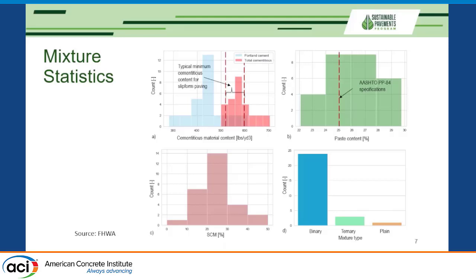Yes, here we go. On the top, I am summarizing the cementitious material content distribution in pounds per cubic yard. Here you can see the red series represents total cementitious content, while this lighter blue, almost invisible, shows just Portland cement. And here we have the recommended typical minimum content of cementitious materials for slip form paving. We can see that we are a little bit higher, on the upper range of this interval.